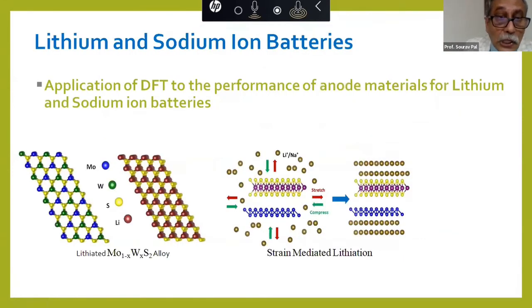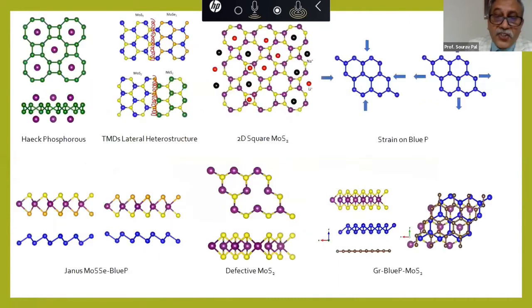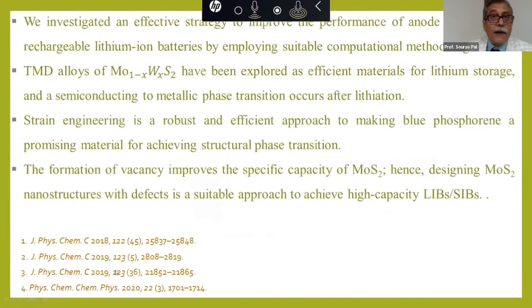We have been very recently working on the lithium and sodium ion battery. This is a very recent work on application of DFT to the performance of the anode materials in particular. And we are looking at the molybdenum sulfide, lithiated molybdenum tungsten sulfide, strain mediated, several ones, phosphorene, 2D square MoS2, strain on blue phosphorene, several different methods we have actually looked at, and we have found very interesting properties. I must just quickly highlight that the molybdenum is very good in terms of the adsorption, but if you want to get all the properties right, then you need tungsten, so that we suggest that the alloy is a good material to use for lithium storage.